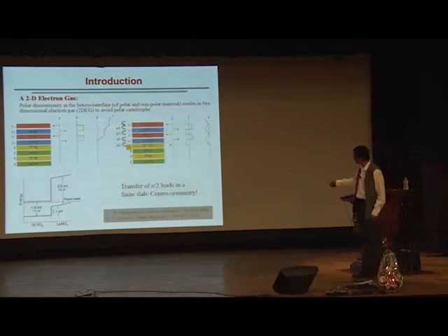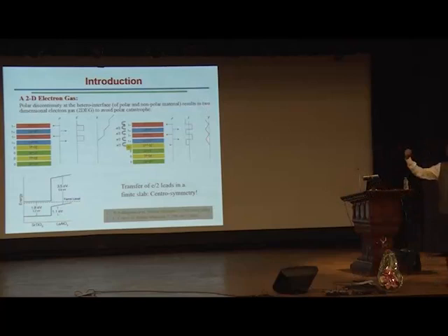It turns out that if you transfer just half an electron and make this titanium 3.5+ instead of titanium 4+, so that you have now half an electron in this interface layer, charge pattern is minus half, then plus 1, minus 1, plus 1, minus 1, then this potential doesn't run away any longer. So you've stabilized that dipolar field, which otherwise was growing up catastrophically, and that transfer of the charge now gives you a two-dimensional electron gas here. And that two-dimensional electron gas was proposed to be the driving force for all this high mobility metal and superconductivity and magnetism, etc. But what's the problem with this?